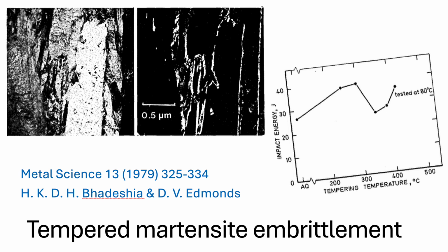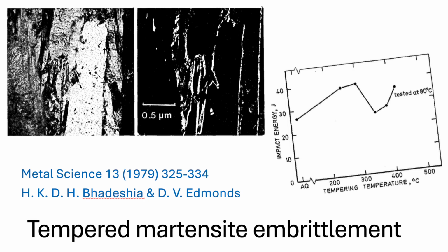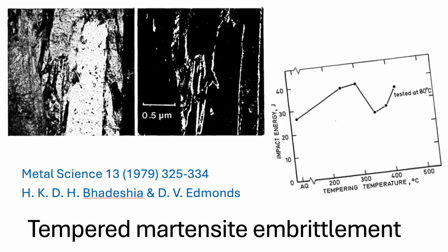What about the third alloy they looked at? The third one was an iron manganese silicon carbon alloy, Fe-Mn-Si-C. This provides yet another angle. How so? This alloy contained very, very little retained austenite to begin with, less than 2%. Almost negligible. Okay. Yet TME was still definitely present. It still showed that characteristic dip in toughness. Yeah, the cause. Well, unsurprisingly, with so little retained austenite available to decompose, the TME here was also primarily attributed to that intralath cementite precipitation coming from the decomposition of the highly supersaturated martensite, similar to the vanadium steel.